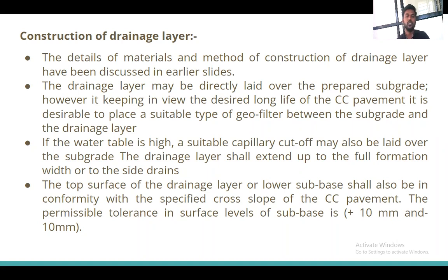Okay. The top surface of the drainage layer or the lower subbase shall also conform with the specified cross slope of the CC pavement. Also, whenever we are providing the drainage layer, that is also maintained with the slope. Okay, whatever camber is designed should be maintained on the drainage layer also, and the surface layer should also be properly maintained within the permissible tolerance limits of plus or minus 10 mm. Okay, for the drainage layer, plus or minus 10 mm permissible tolerance is allowed.